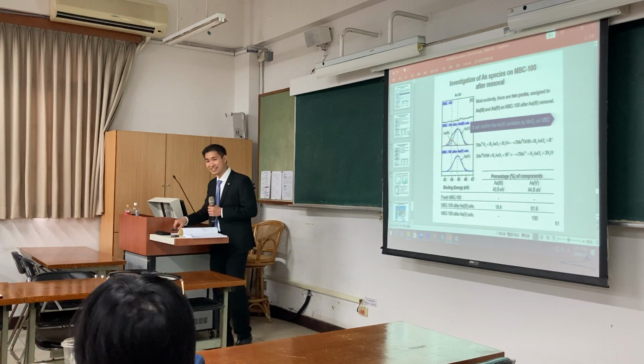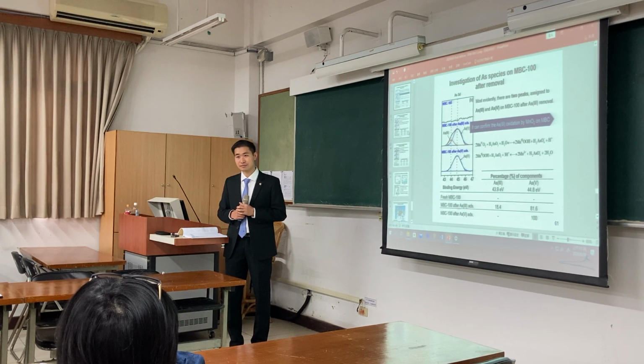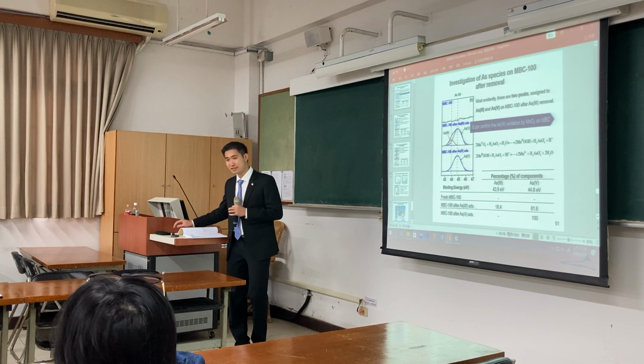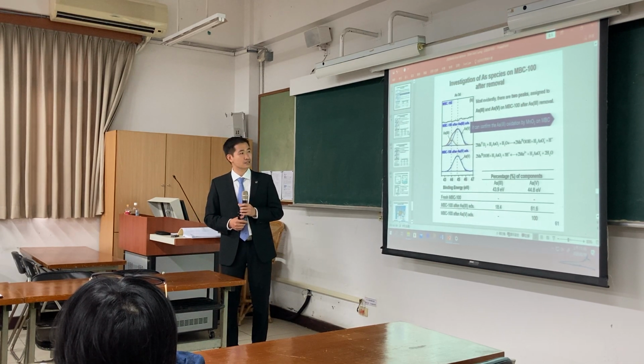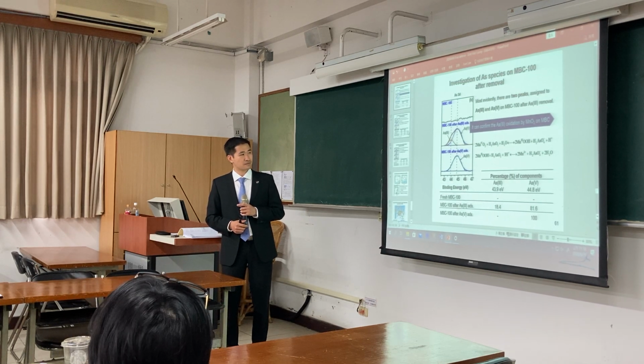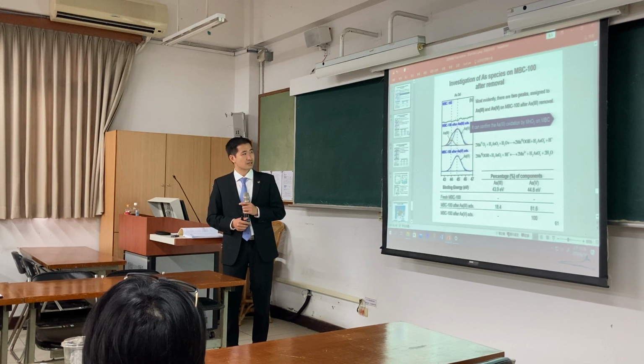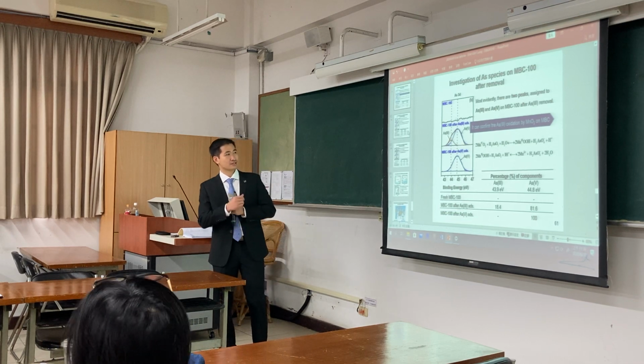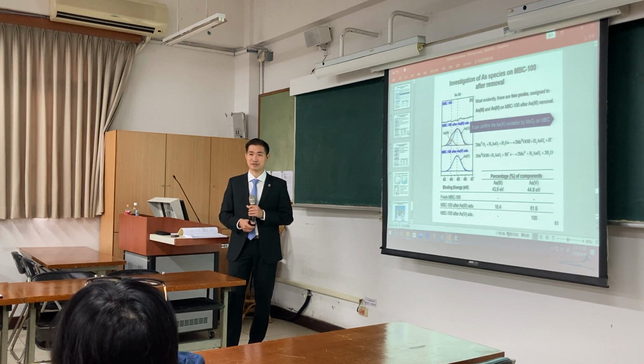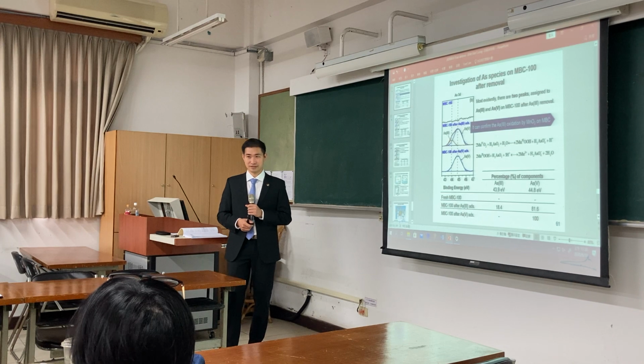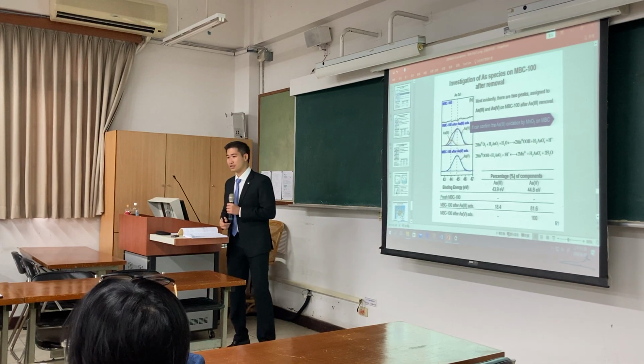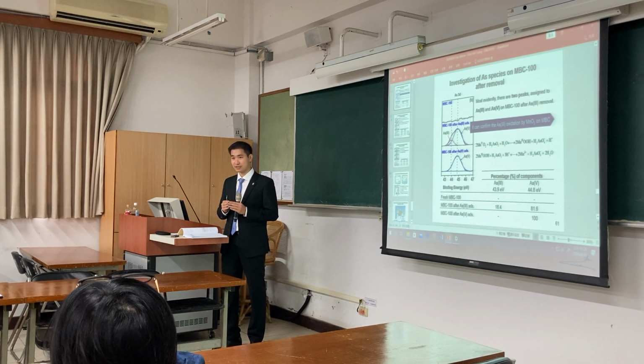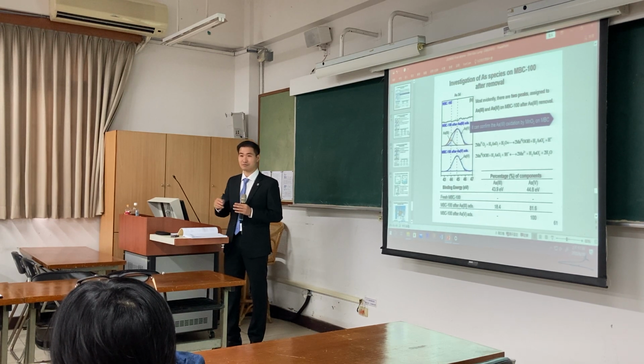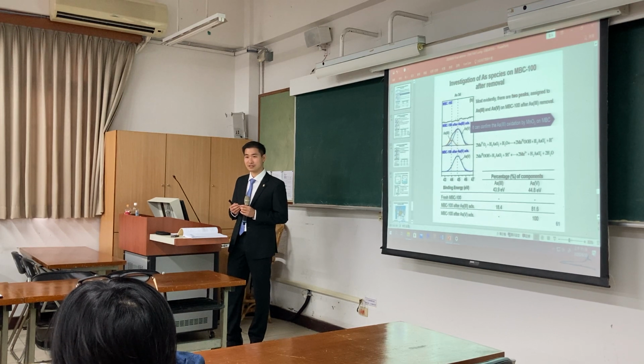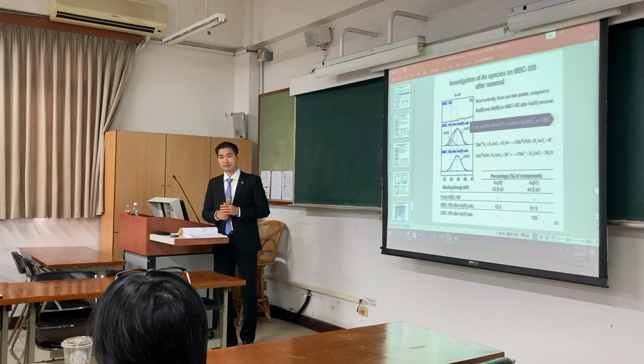Okay, but last one. Can I ask a follow-up question? Can dissolved oxygen oxidize arsenic 3 to arsenic 5? The reason I'm asking is, I think you are doing your experiment in the presence of DO, right? You don't purge it with nitrogen. There are some studies that conducted experiments to observe the effect of oxygen. So if dissolved oxygen can oxidize arsenic 3, then you don't really know the contribution of MnO2 versus oxygen.